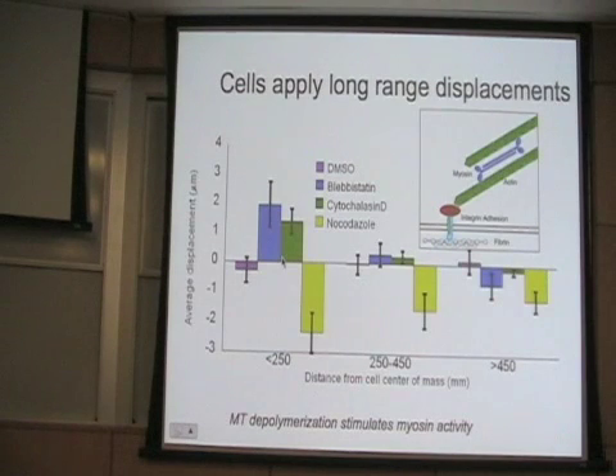So here is one example of an average bead displacement measured circumferentially everywhere in a little zone that is either within 250 microns of the edge of the cell or more than 250 microns away. And even up to 250 microns away, beads are being moved a couple of microns. We can tell that because if we poison the contraction with blebistatin or cytochalasin, we get these motions. But even 400, 500 microns away, the beads are still noticeably moving. It's only when we get past half a millimeter that we can't see statistically significant movements.